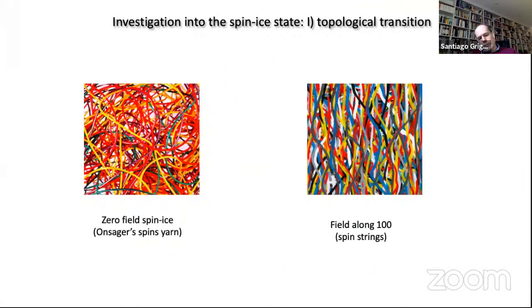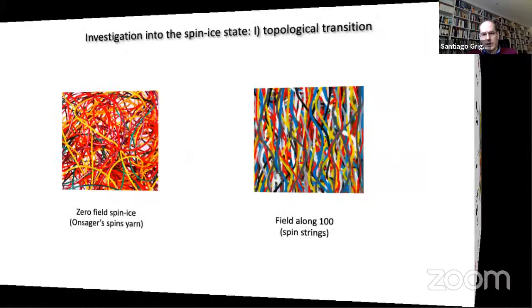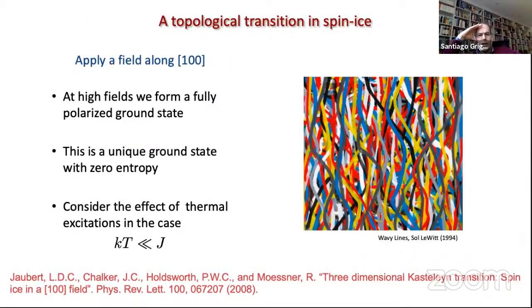Okay, so essentially that's the brief introduction I wanted to give you about spin ice, and now I want to tell you about two different problems in spin ice which we've been working on. One of them, this one in particular, is still work in progress. So what I want to tell you about is a topological transition you can get in spin ice. The idea is this: now you take your spin ice material and you apply a field along one of the principal axes, let's say 100. If you do that, you polarize this ground state and you get a single state. So you lose this residual entropy, you get a single state with 0 entropy.